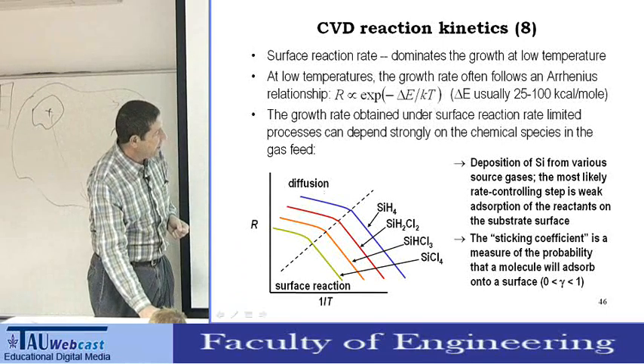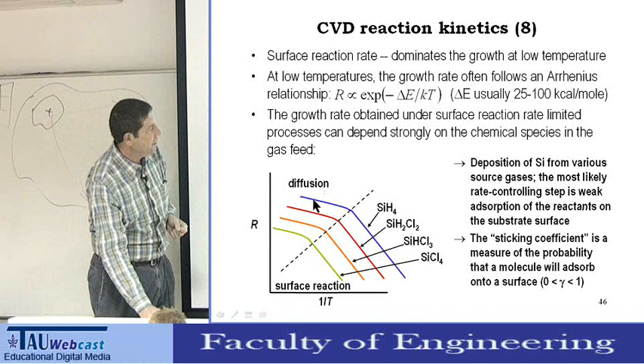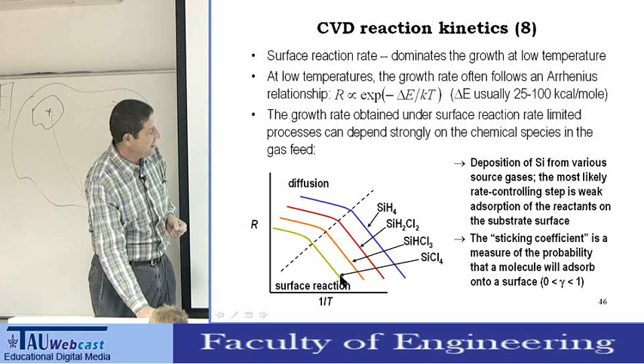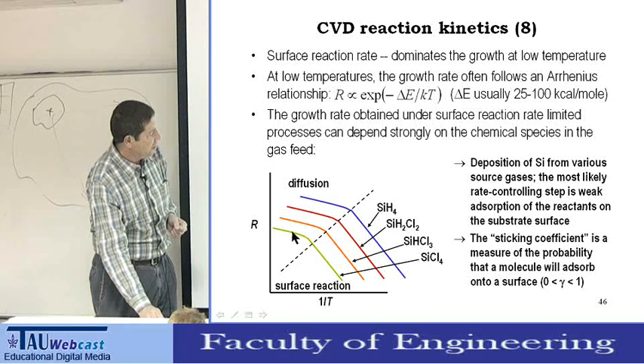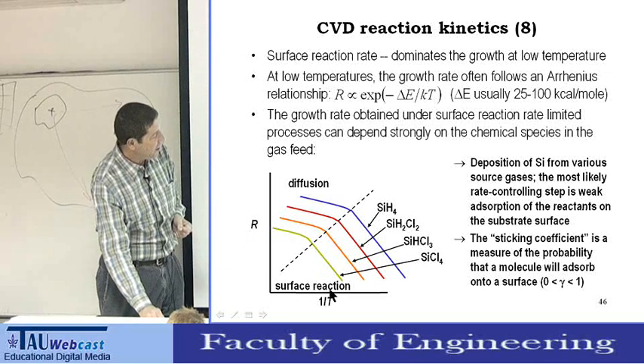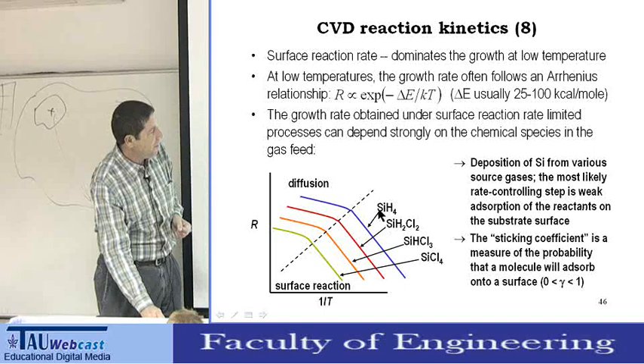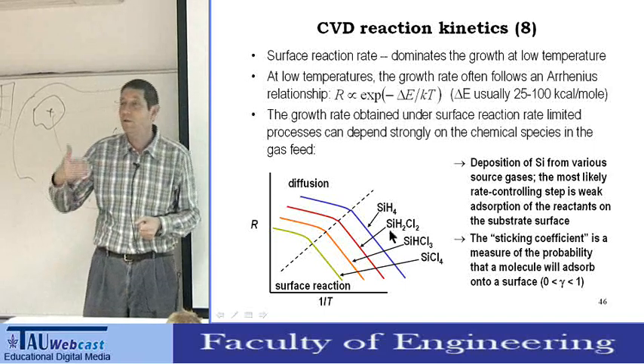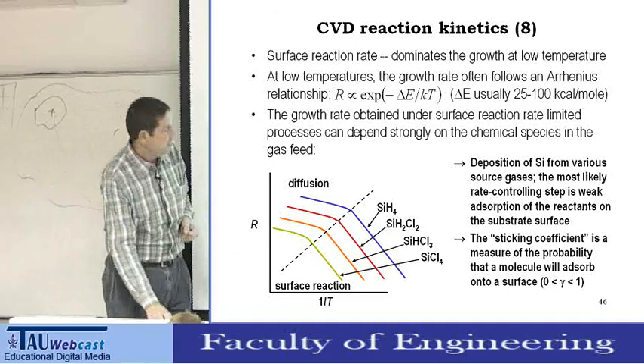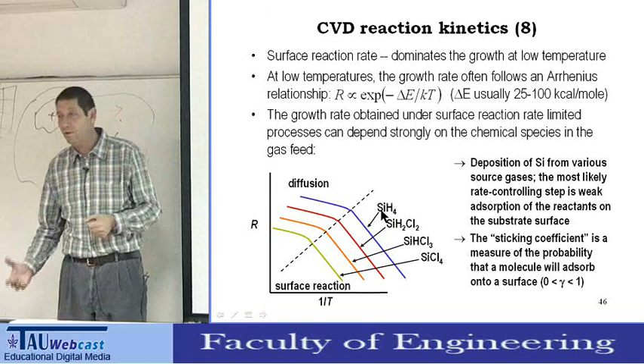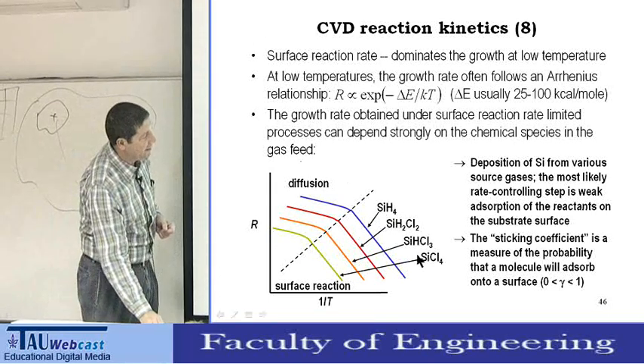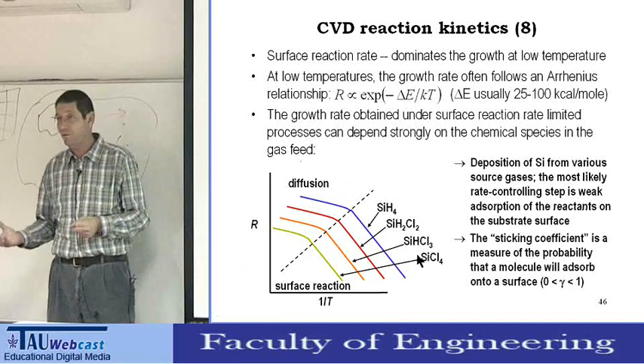At higher temperature we start to be limited by diffusion. Not surprisingly, the gas with the slowest deposition rate has its turning point — where we switch from surface-reaction mode to diffusion-reaction mode — at a higher temperature. All these materials are depositing silicon. Typically SiH4 is used for polysilicon, and SiCl4 is used for epitaxy of silicon.